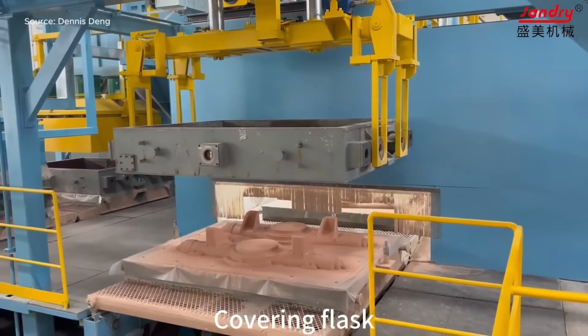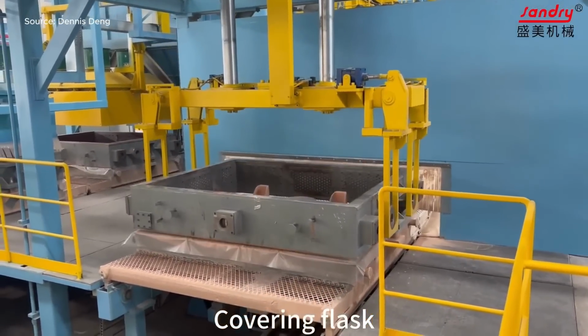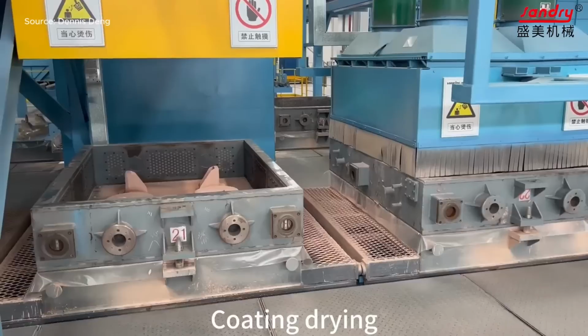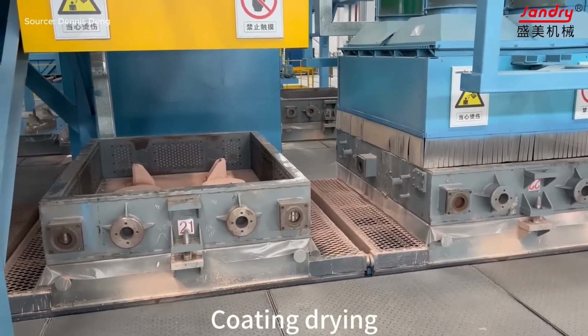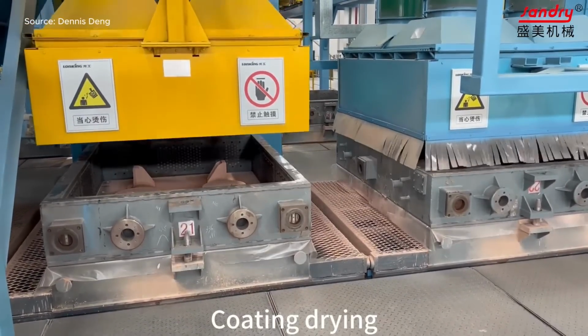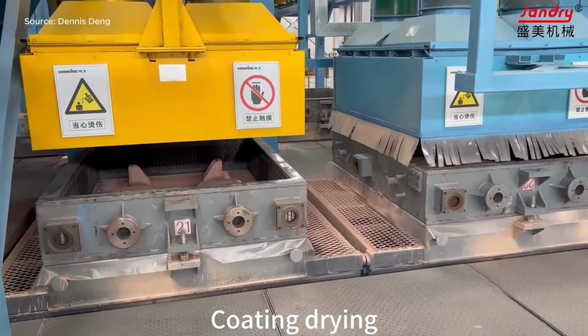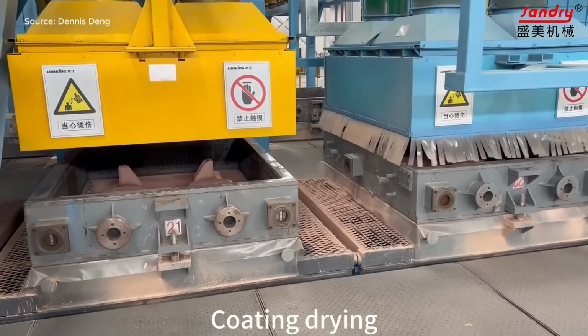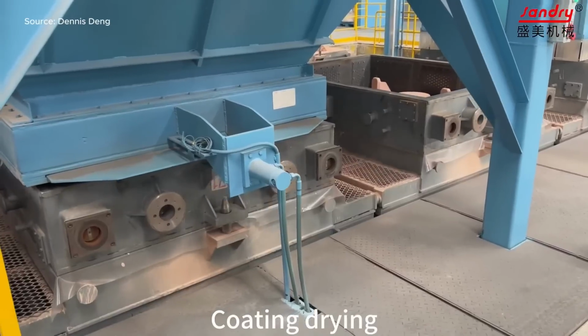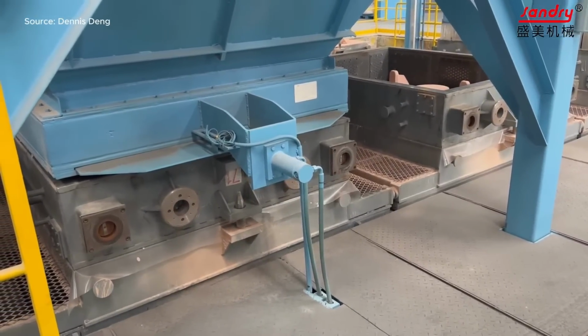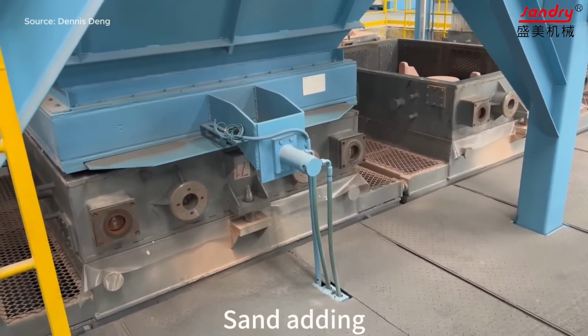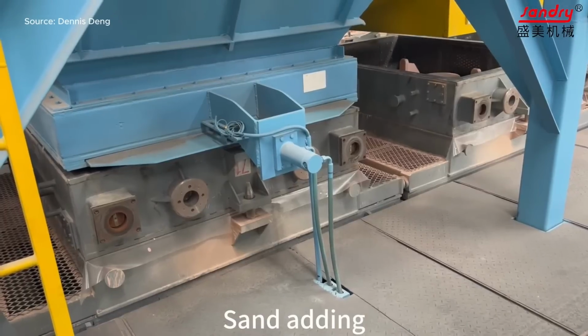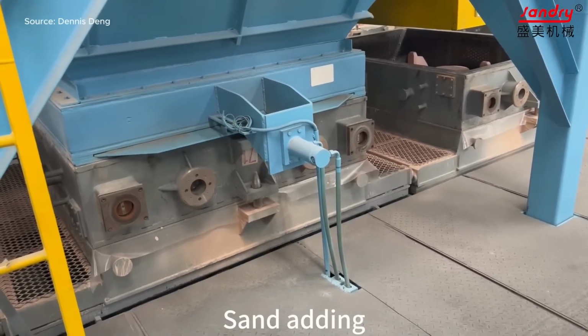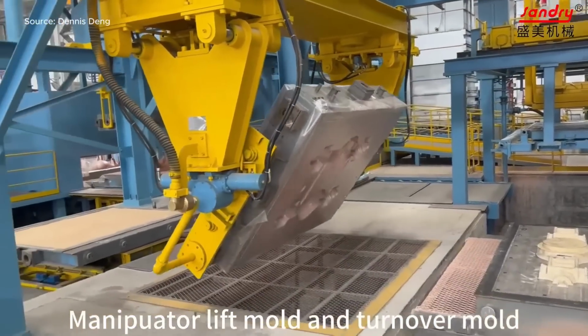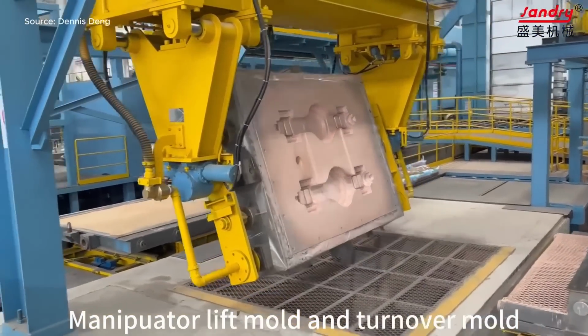After coating, the flask returns to the molding station, where vacuum is applied to secure the film. Dry, unbonded sand is added to the flask and compacted under vacuum, which holds the sand rigidly in place without chemical binders. A manipulator then lifts and inverts the mold to expose the cavity. The core setting station inserts pre-made sand cores for internal features, and the two mold halves are assembled precisely. Molten iron is prepared and transferred into the pouring station.